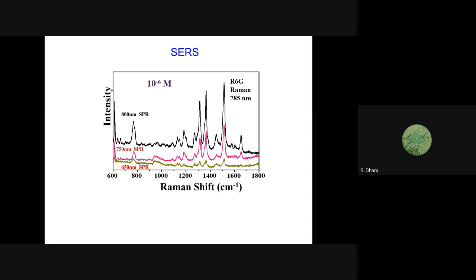And this scattering phenomenon is very low without that. Actually, we should have shown it without any SERS effect. Now with gold nanoparticles or gold nanorods in this case, using different surface plasmon peaks, we could detect up to 1 micromolar. Next, please.